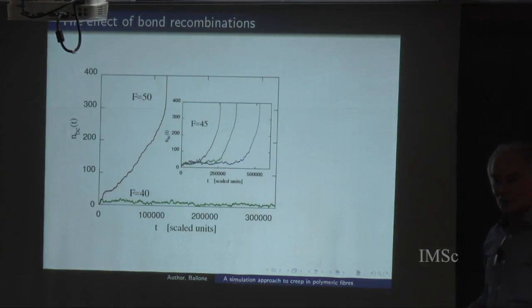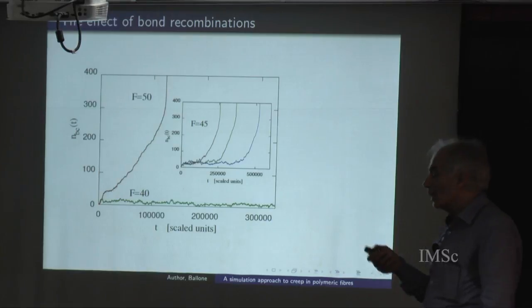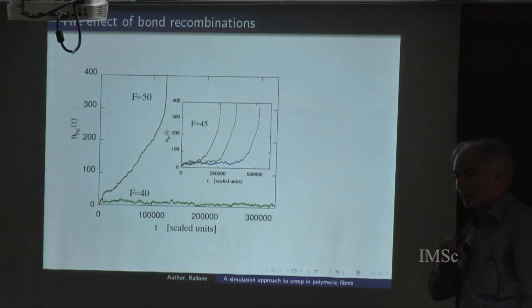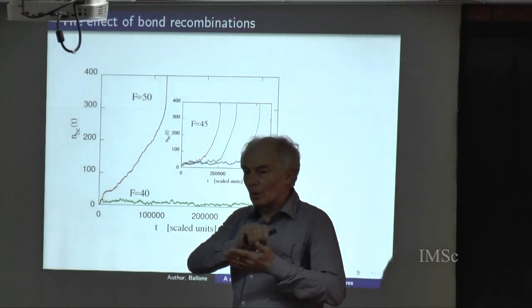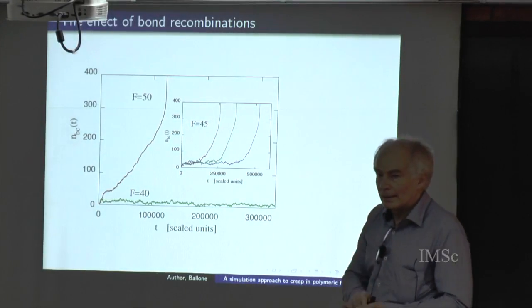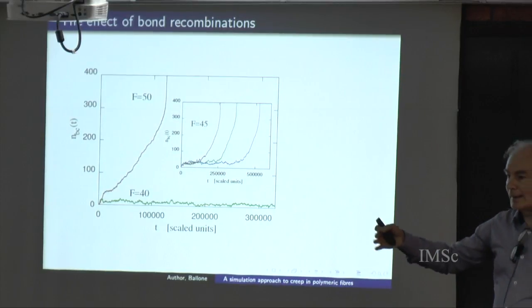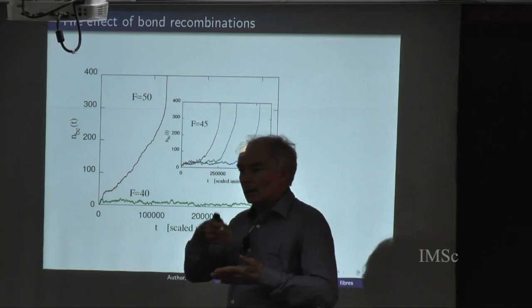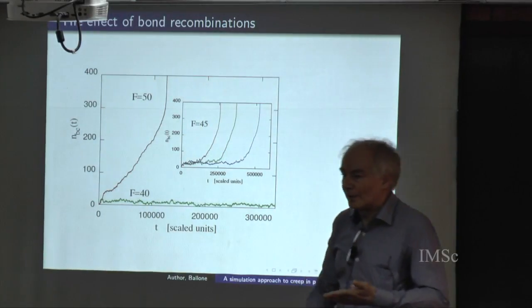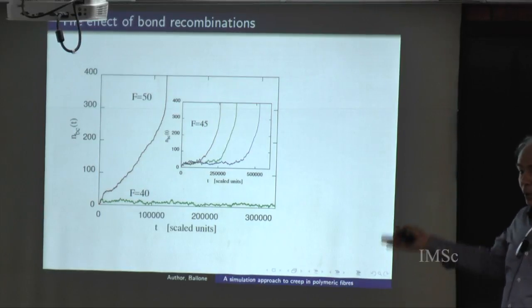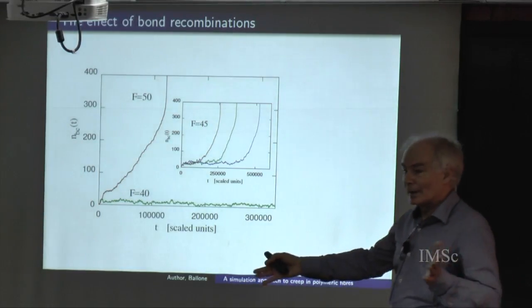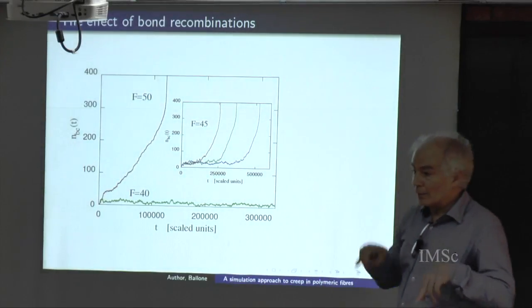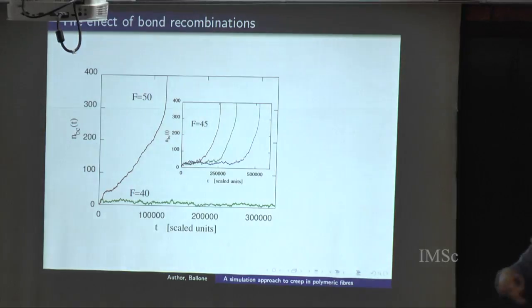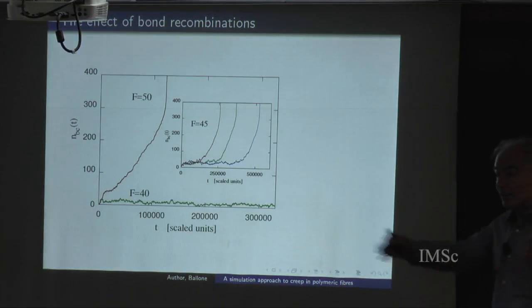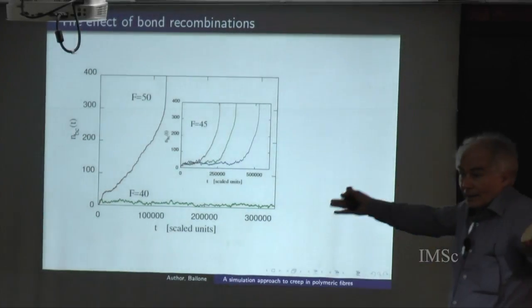I told you that we made the choice of having no recombination, and I said that it almost doesn't matter. Instead, it has a dramatic effect, because if you have bond recombination, you have a steady rate of bond recombination. If the tension and the temperature are such that the natural rate of breaking bonds by fluctuation is below that, the bundle will not break. So what I said before, that every bundle is unstable, is not true if you have bond recombination, because recombination will take place at some rate. If you break bonds at a lower rate, then it is stable.